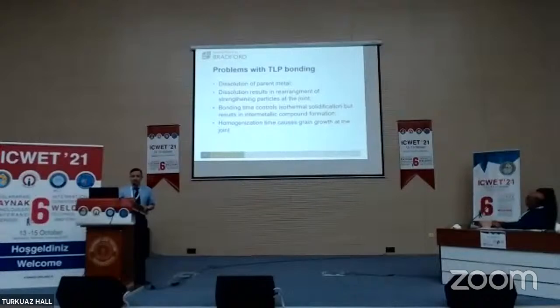Dissolution results in a change in the strengthening of the particles and the strengthening of the joint. Bonding time can control the isothermal solidification process, and that can control intermetallic formation, but intermetallics do not disappear. And then homogenization, which is the last step in the joining process, unfortunately can cause grain growth. And grain growth then means you have a weaker bulk material.